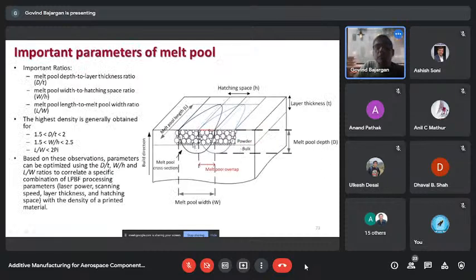So this basically is to get a sound deposit, to ensure the bonding between one layer to another layer when deposition is happening. The important parameters, when we talk about process optimization, mainly three parameters which are really important are laser power, then scan speed, the speed at which the laser scans the build platform, and then the hatch spacing, meaning the distance between the first scan and the next scan.